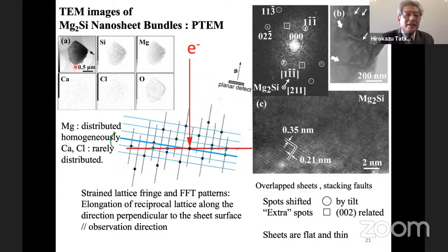from the substrate. So this is a magnesium silicide sheet. From the TEM observations, it is confirmed this is magnesium silicide. And it's interesting, these spots come from this pattern; lattice fringes are not bulk features. This pattern is elongated in these directions, and there is a new spot. So these features prove this sheet is very thin. These features appear by tilting the sample compared to the electron beam direction.